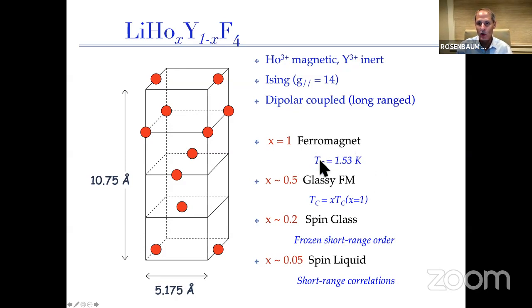So the Curie temperature of this material is 1.53 Kelvin. It's low because it's dipolar. So if it were an exchange coupled magnet, you'd expect to see something, say, of order 1,000 Kelvin. So as you dilute now, substitutionally replacing the holmium, the dipole concentration, with yttrium, which is non-magnetic, you still wind up with a ferromagnetic state, but you get some glassiness because of this competition between the ferromagnetism and the antiferromagnetism. And the Curie temperature just goes linear. It's a 1 over r cubed interaction in three-dimensional space.